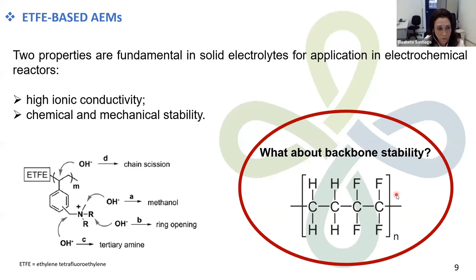But I will have a large number of functional groups if I have a large number of side chains. So if I have a very good radiation degree of grafting, I will have a large number of functional groups, and I can achieve higher ionic conductivity. On the other side, the chemical and mechanical stability are related to attacks from OH on different parts of the membrane, and radiation that can promote some degradation on the backbone. But we have a focus on the studies involving the backbone stability. That's what we're going to talk about.